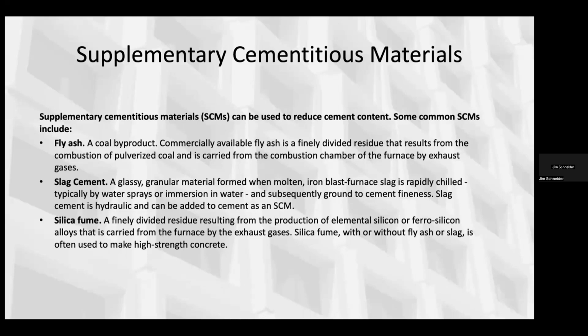As a coal byproduct, commercially available fly ash is a finely divided residue that results from the combustion of pulverized coal and is carried from the combustion chamber of the furnace by exhaust gases. The thing with fly ash is you can use it in certain percentages. In the precast industry, we've used it quite a bit for a while. It depends. It's something you need to talk to your precaster about, depending on the application, what you're looking for, curing time and all that. That sort of determines what percentage of it you can use. And the other thing with fly ash is that, frankly, as we hopefully start to use less coal, that will become less available. So we have to certainly be thinking about other things as well.